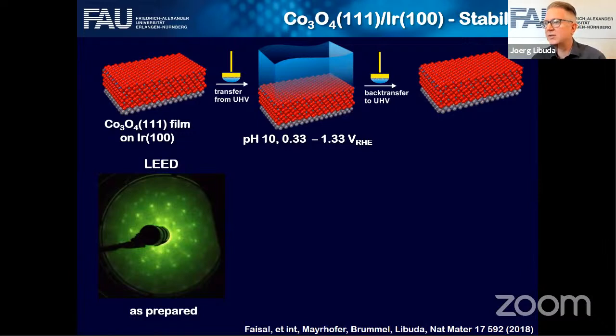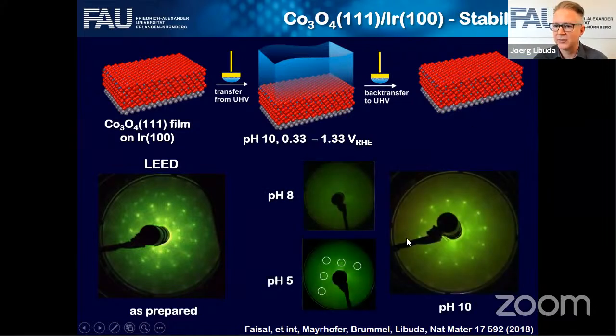And if you do the experiments under the right conditions and then bring back this sample, you will still see the same LEED pattern. So you may say the LEED pattern now is a little bit more fuzzy, diffuse. That is true. That's because the surface is hydroxylated and there are also electrolytes left over on the surface, but the long range structure is the same. So this film in principle survives this transfer and quite extended experiments in the electrolyte.